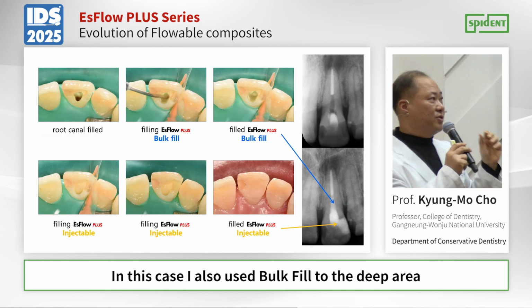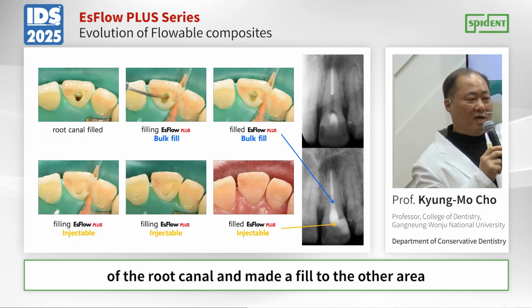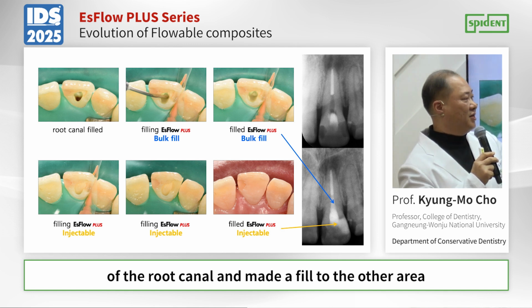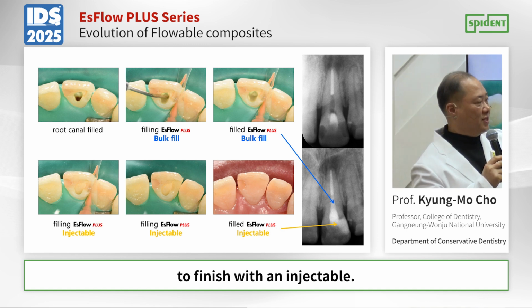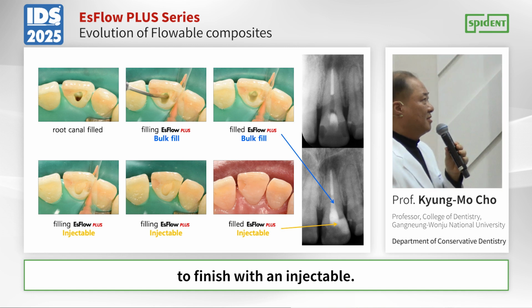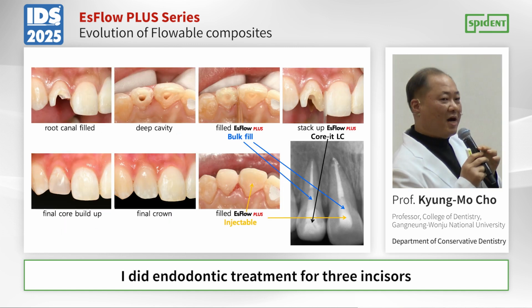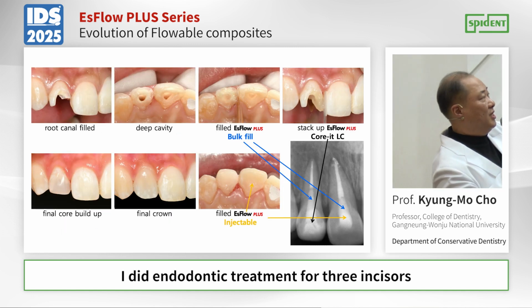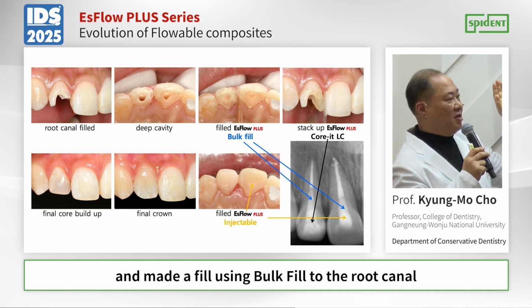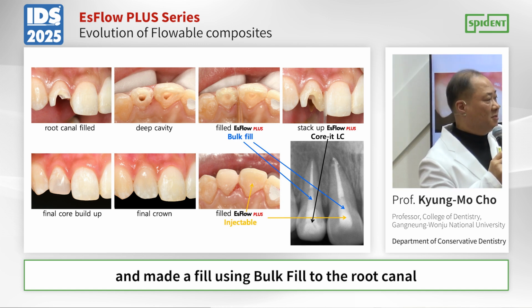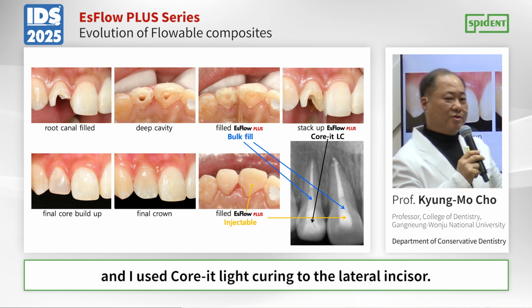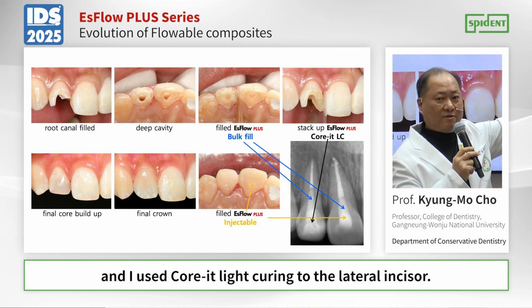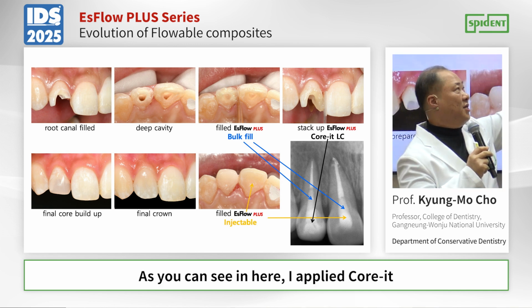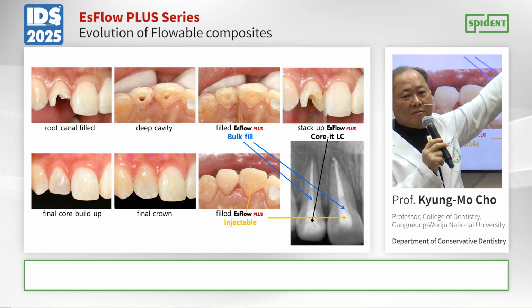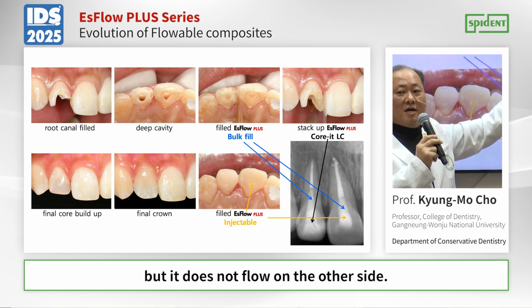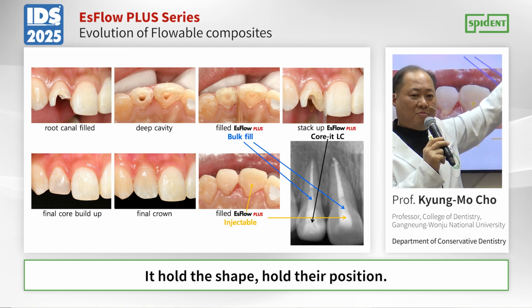In this case, I also used the bulk fill in the deep area of a root canal and made a fill in the other area to finish with the injectable. I did endodontic treatment for 3 incisors and made a fill using bulk fill in the root canal, and I used Core-it LC for the lateral incisor. As you can see in here, I applied Core-it, it does not flow to the other side. It holds the shape, holds its position.